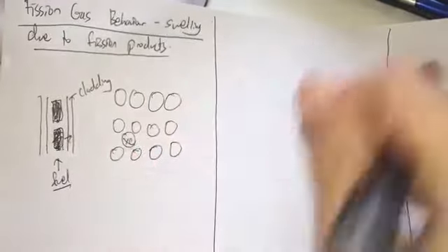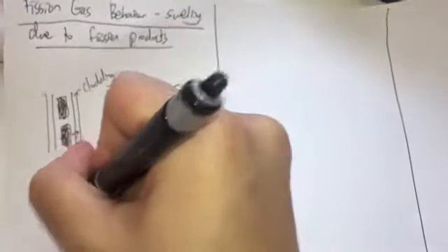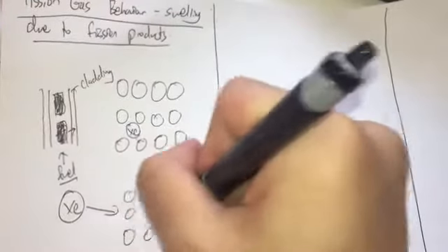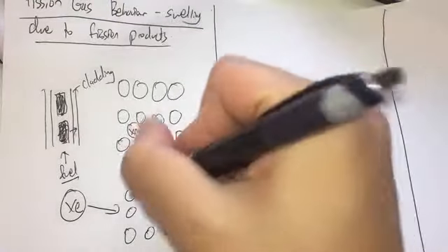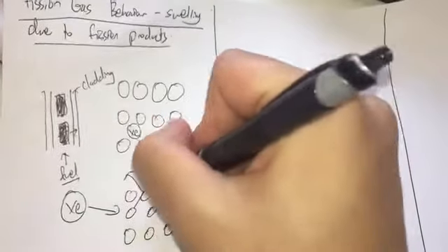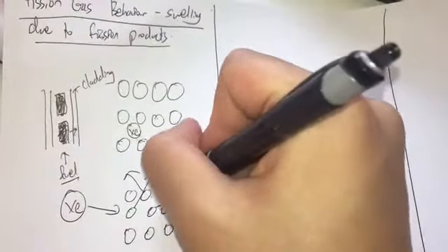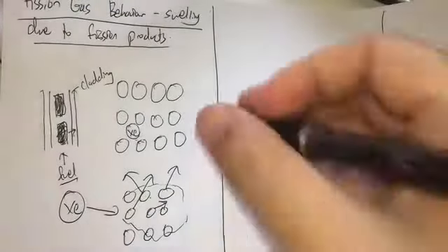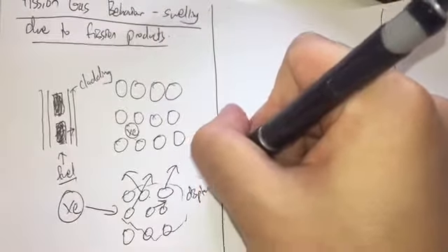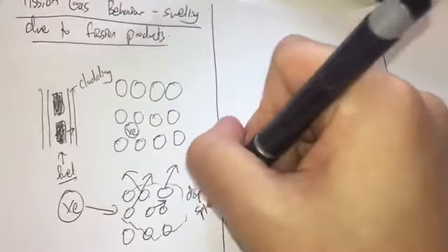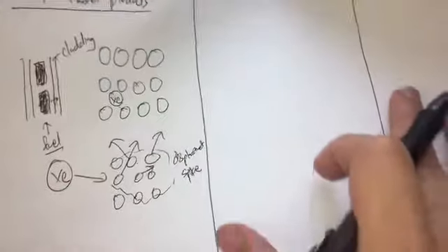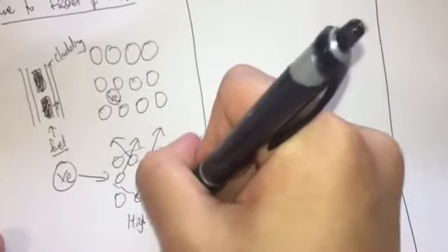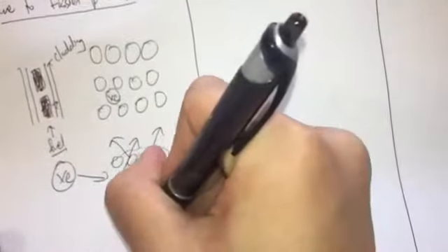Why? Because when the xenon comes into the lattice, it will make a displacement spike. So the PKAs will go here, then it will cause a displacement cascade, so that maybe here, the part I'm circling, they will have a displacement spike where there is a high concentration of vacancies. Excuse me. High concentration of vacancies.